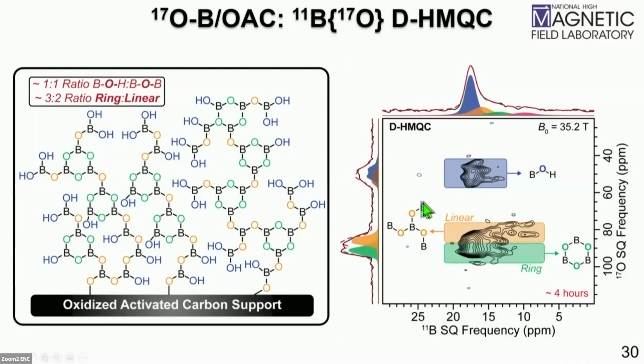Now, what is also interesting is that if you look at these lower frequency boron NMR signals, these are presumably coming from boron grafting to the carbon surface. They primarily correlate to the linear type bridging oxygen atoms, suggesting that this layer is linearly grafted to the carbon support, which is also probably not too surprising when you try to draw what the structure looks like.